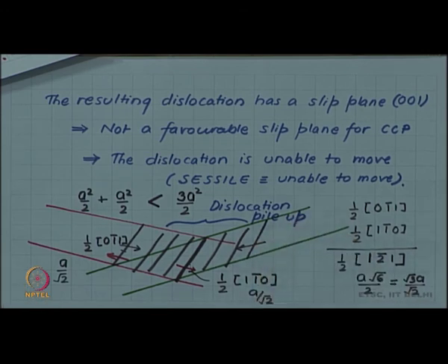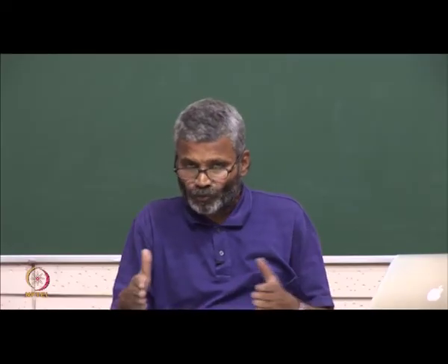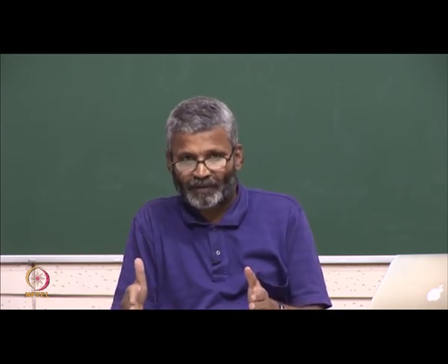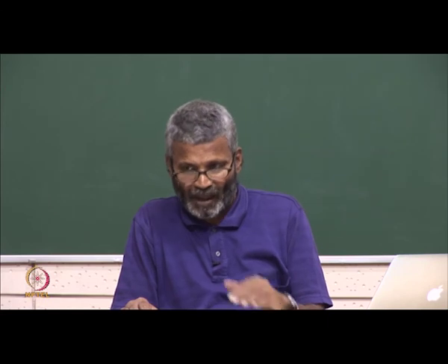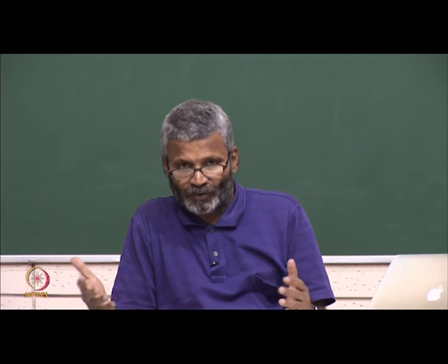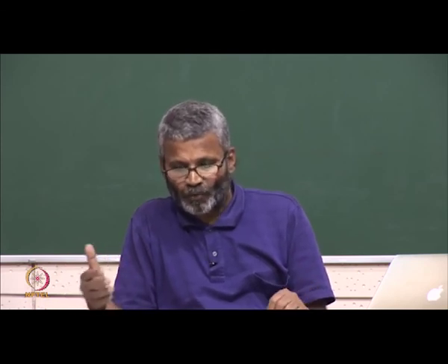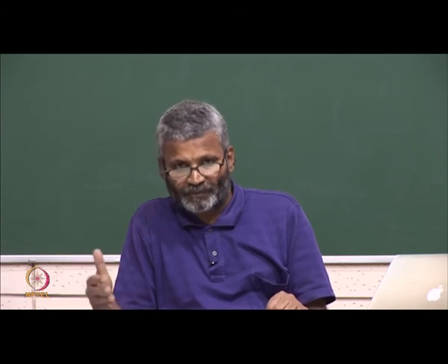So, we have seen one specific example of how dislocation interaction can create such a sessile dislocation, and the result where, due to the formation of a sessile dislocation, a traffic jam of dislocations takes place, dislocation movement becomes difficult, and thus finally you will have a harder material. You will have a harder material because plastic deformation is becoming more difficult, and this is what is strain hardening.